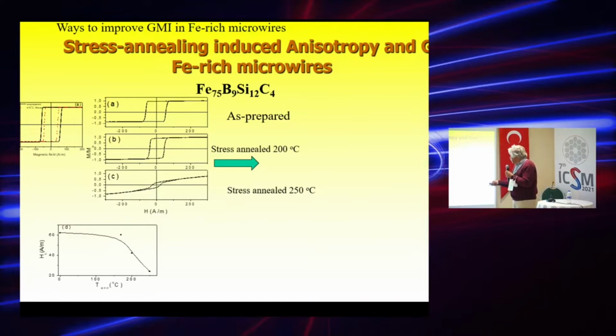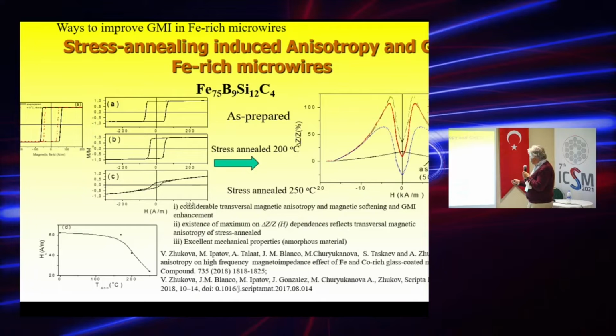However, they recently found that if you apply stress during the annealing, the hysteresis loop becomes different, so coercivity drastically drops and the permeability increases. So here is also the plot. This is one of the first papers.